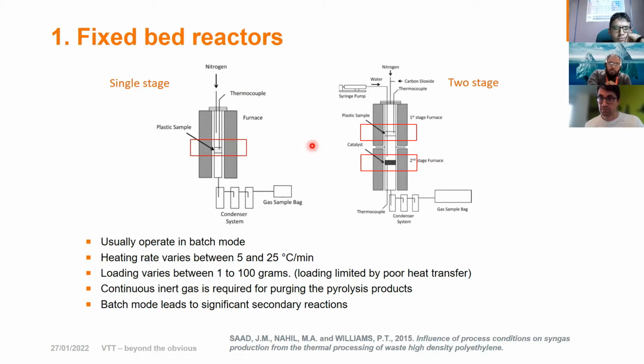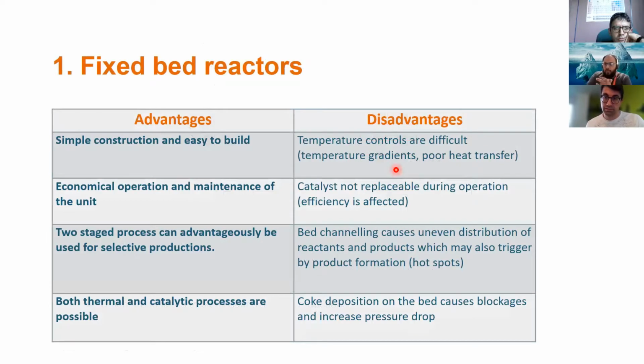It can be used as a thermal mode, which is a single stage. You see that only plastic is degraded and the products are condensed. But on the other hand, it can also be used in two stages, which means that the plastic is degraded here and the vapors are in contact with some sort of catalyst in a second stage. So catalytic upgrading of the vapors happens here. But these are lab scale units and good for screening, not really for any production.